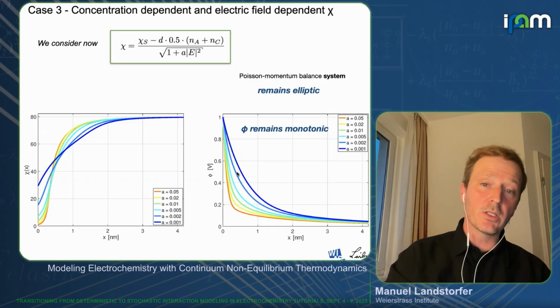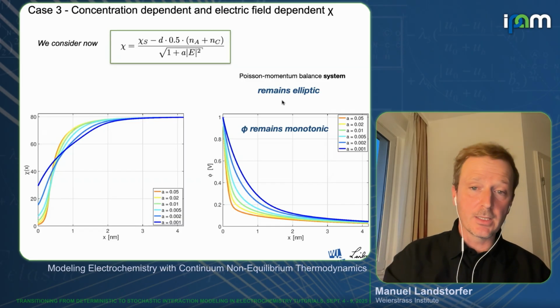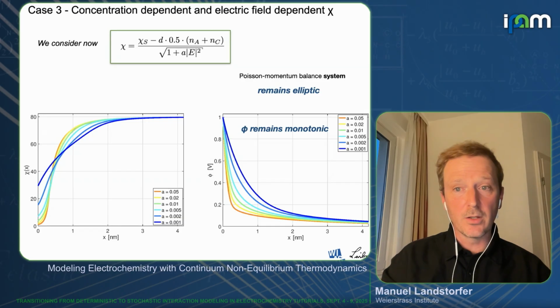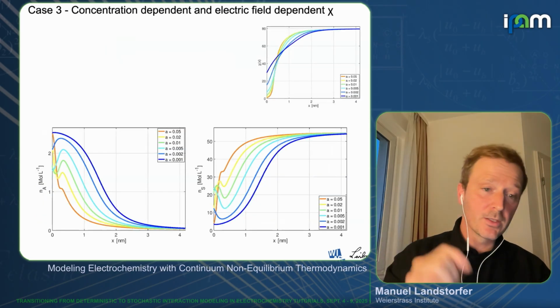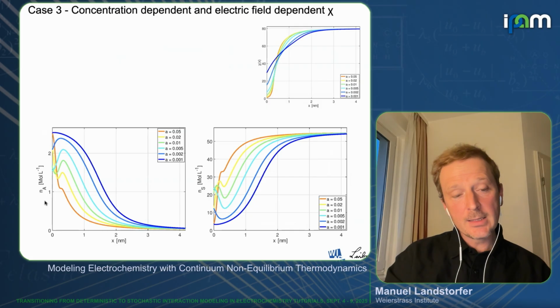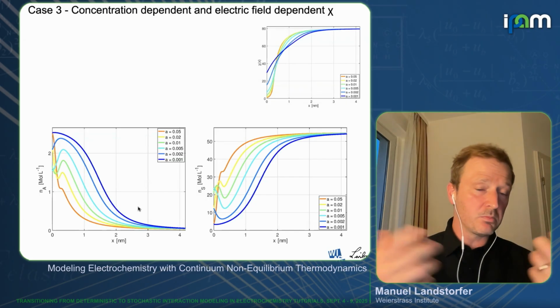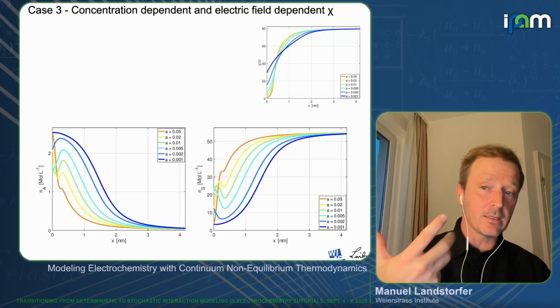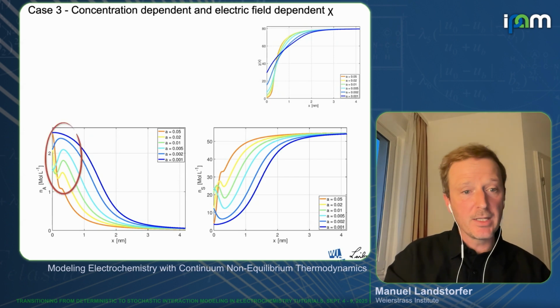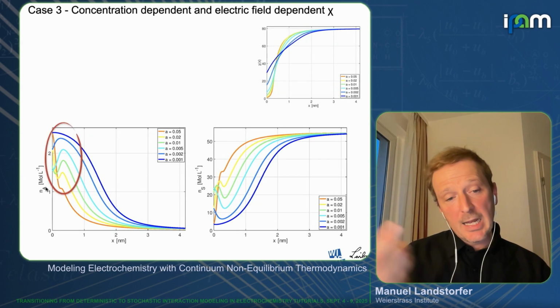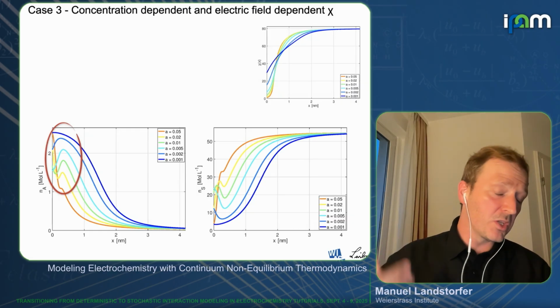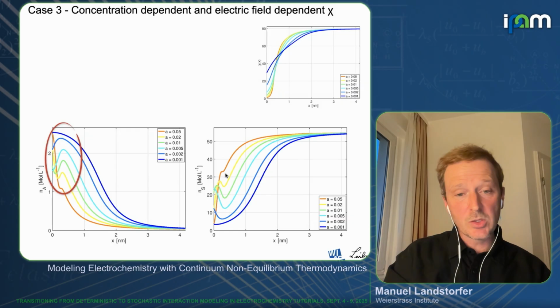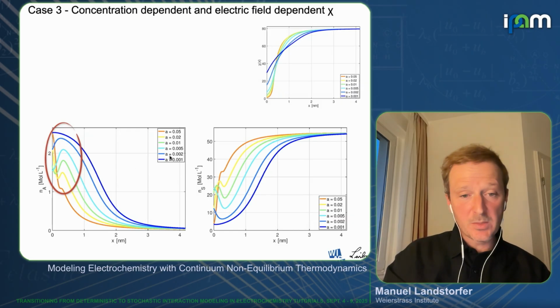So if phi would become non-monotonic, then this could also change the ellipticity or the solvability of the underlying Poisson equation. Surprisingly, what you can now find are oscillations in space for the anion or the solvent concentrations, just because it's now a balance of the electric field strength between attracting anions, and then somehow it's becoming more favorable to agglomerate against solvent, dependent here on this parameter A.